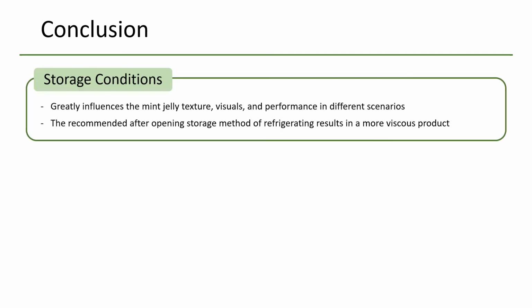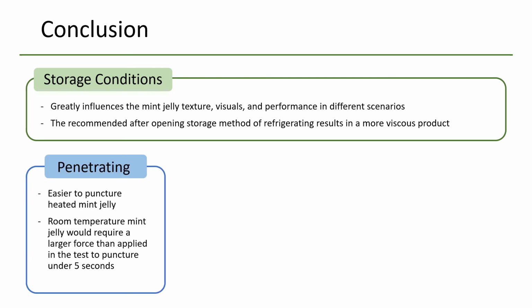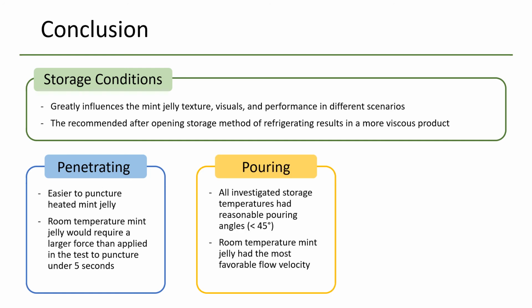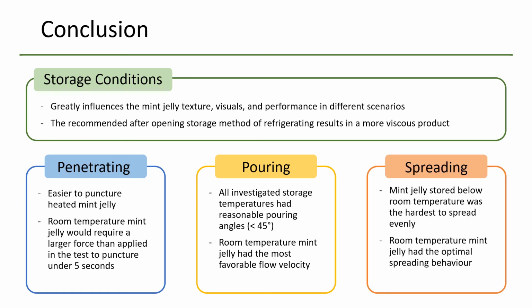To conclude, the performance of Cole's mint jelly was evaluated in terms of storage conditions, penetrating, pouring, and spreading the product. Storage temperature greatly affected the performance in different scenarios. The mint jelly was the easiest to puncture at higher temperatures. If at room temperature, a larger force was needed to reach a depth of 2 centimeters under 5 seconds. The product had acceptable pouring angles for all storage temperatures, but had the most favorable flow velocity at room temperature. Similarly, room temperature had the optimal spreading behavior. So overall, Cole's mint jelly performs best when at room temperature.